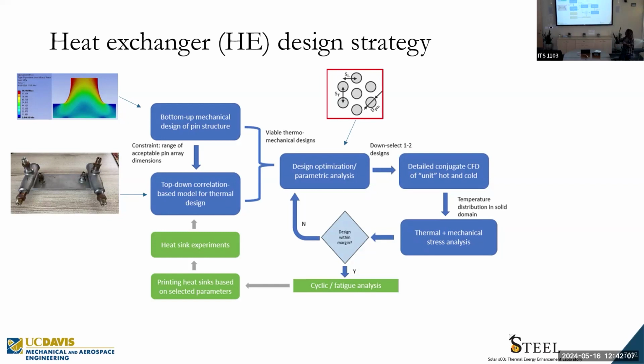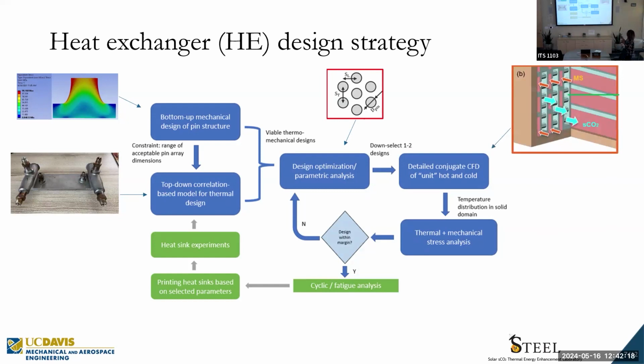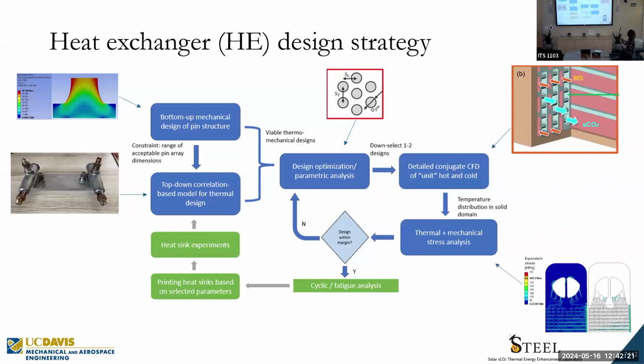After selecting the correlation, we conducted an optimization and parametric study where we go back to the set of pin diameter, wall thickness, channel width, and all that, to come up with a best case scenario that we'll be using for the heat exchanger. After selecting this best case scenario, we run some CFD and FEA simulation. In the CFD, we want to look at the thermal performance, but also obtain the temperature distribution within the heat exchanger so that we can assess the thermal stresses. Thermal stresses will be added to the mechanical load, the pressures that we have in the unit, to have a combined thermal-mechanical stress of the heat exchanger.